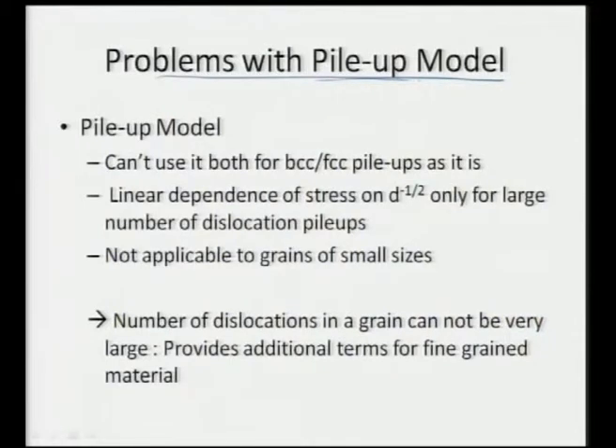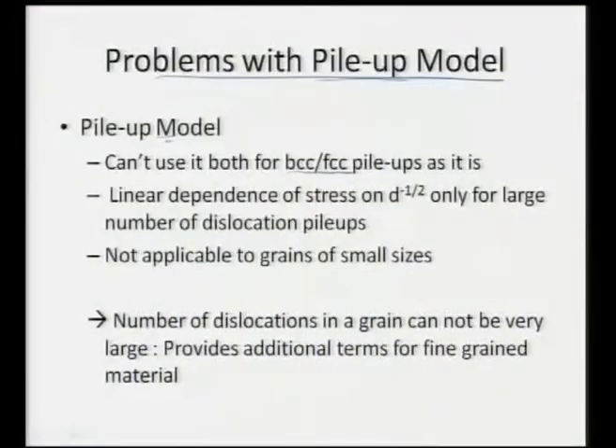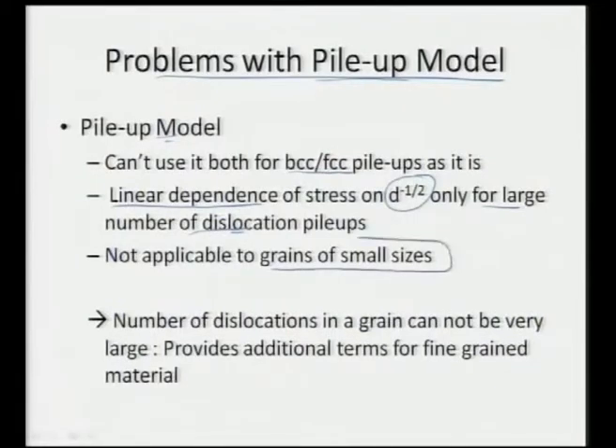Though it has been said that dislocations start to pile up near the grain boundary to initiate stress or enhance strain hardening, the pile-up model cannot be used as it is for both BCC as well as FCC. Also, there is a linear dependence of stress on d^(−1/2), but only for large number of dislocation pile-ups. This model is valid only for grain size approximately till 1 micrometer; below that we do not have enough dislocation pile-ups, so the pile-up model does not become applicable.